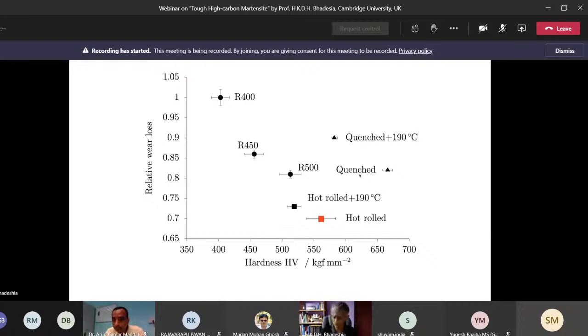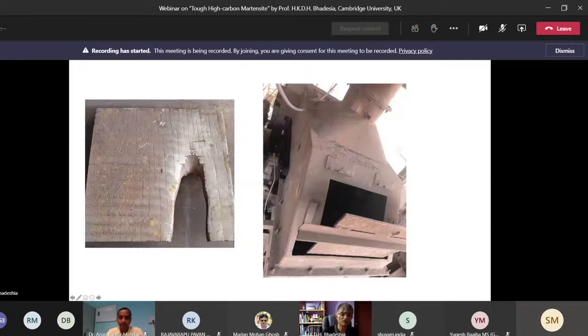So what we've done is we've installed this steel in a particular part of the Tata Steel production plant in Jamshedpur. So this is a particular chute where minerals fall onto a steel plate here. And the steel plate conventionally is a mild steel plate with a very expensive hard-facing alloy, which is iron chrome carbon, deposited onto it by welding. Okay, so you can imagine that not only is the welding alloy expensive, but also the fact that you have to deposit the material on there. And eventually, the mineral impacting on this will completely wear the material out.